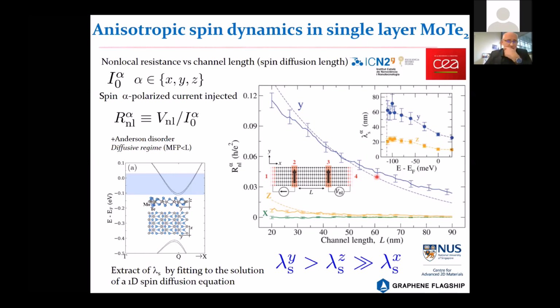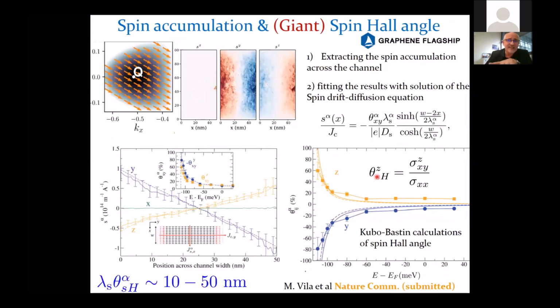And then we could also investigate the spin accumulation and the spin Hall angle, and compute the spin Hall angle, which we also found to be energy dependent and which is up to 80%, close to the band edge. And as a result, our figure of merit could get to this very, very large value, which is really unprecedented